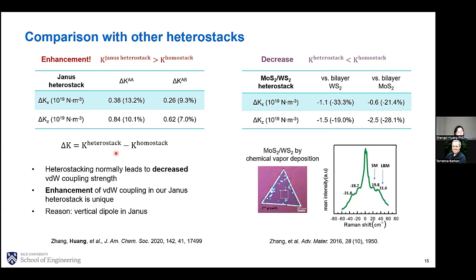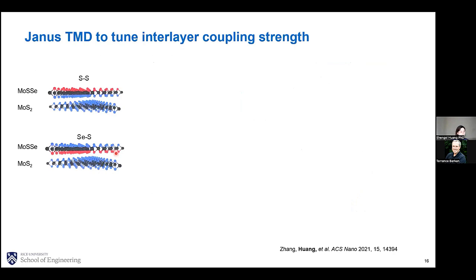Now we have seen the Janus can increase the interlayer coupling strength, which is very exciting. So our question naturally is whether we can further tune this interlayer coupling strength. Well, of course, the answer is yes. You can already see one solution here. We can tune this interlayer coupling by changing the vertical dipole direction. For example, we can make this SS interface by putting this Se layer on the top. And we can also flip this MoSSe layer by forming this SeS interface.